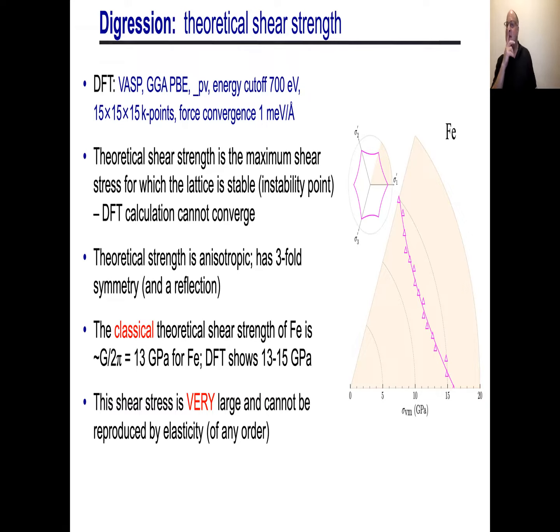But the point I want to make is this theoretical strength means that's the maximum shear stress I should be able to apply in principle. It turns out that it's quite large. And I can guarantee that along this line where the system loses stability, no elastic theory could possibly get that right. It doesn't matter how high order the theory is. So second order, third order, fourth order, fifth order elasticity cannot get it right. So the question is, how well does elasticity work here? And I'm going through this because I'm going to use it later on. So let me show you how well it works.